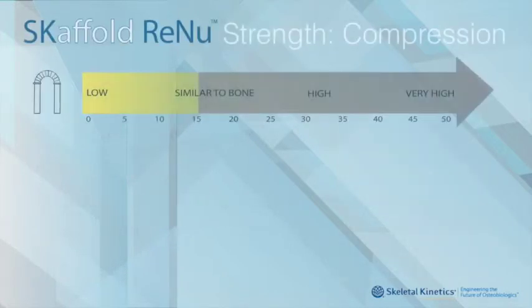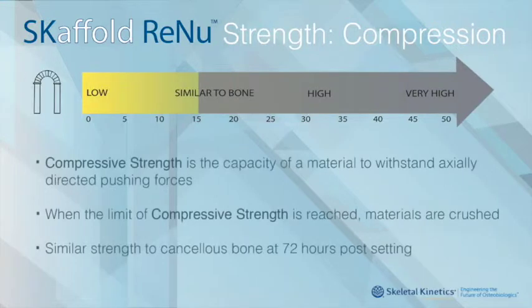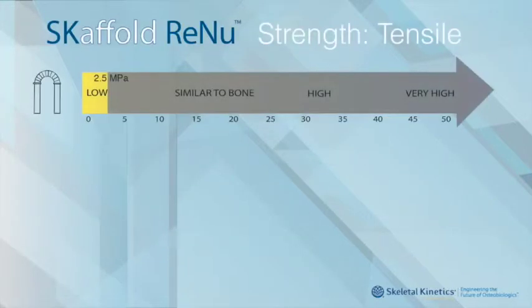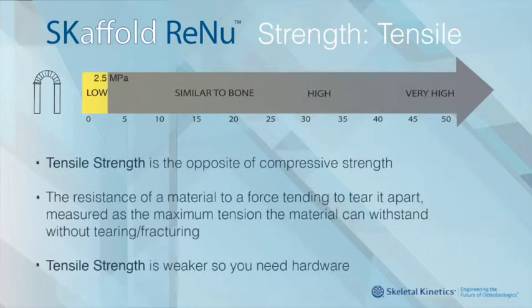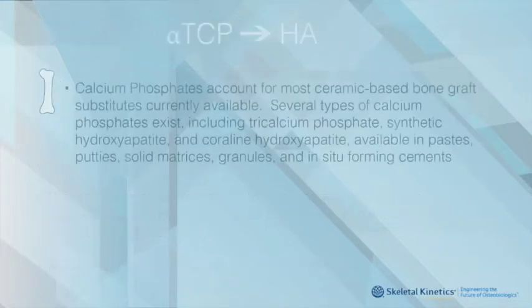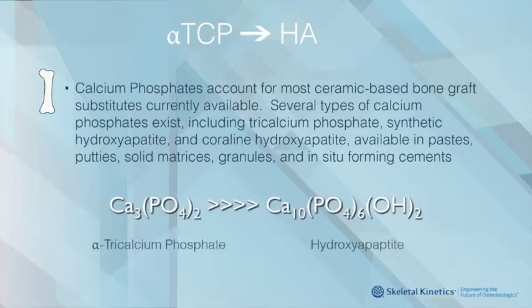First, we'll look at compressive strength. Renu shows strength characteristics similar to that of native bone at about 15 megapascals. When reviewing the tensile strength of Renu, we see it measures at 2.5 megapascals. While this is at the low end of bone, it is higher than most grafts on the market except for scaffold.